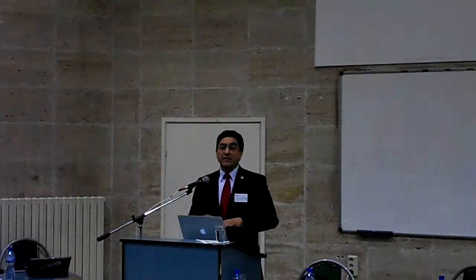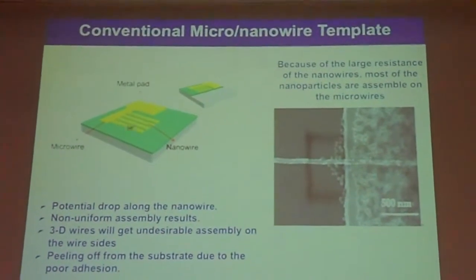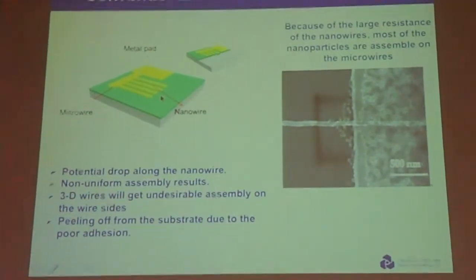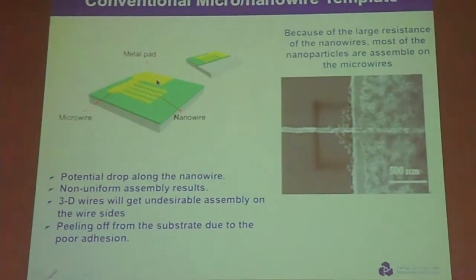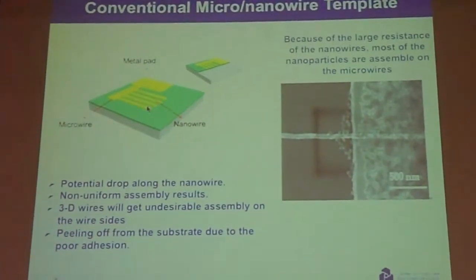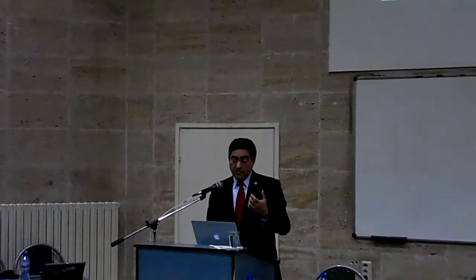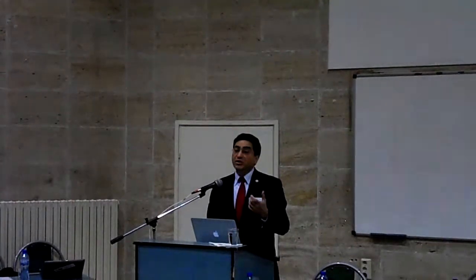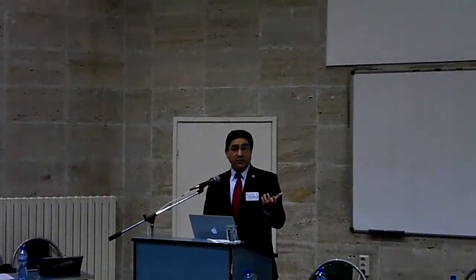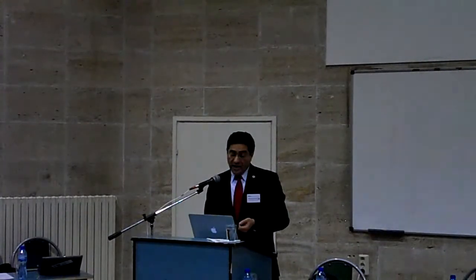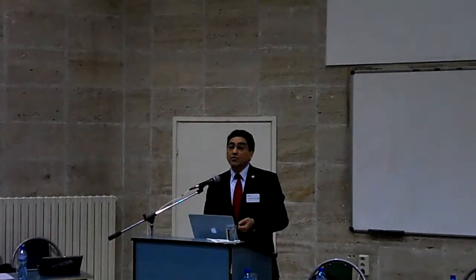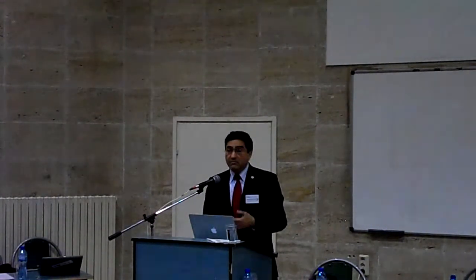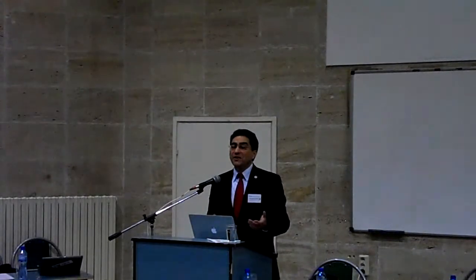So what we did is we had the nanowires, like you see here, on insulator, and we applied voltage, like I told you, 2-3 volts, and it worked for microscale assembly or structure, but it didn't work for small scale. So here, for example, you do the inking and you do the assembly of the particles, for example, on nanotubes. The large structures have the right voltage, but the small structures have such a high resistance that you don't get enough voltage, so you don't attract anything. And you can see here, this wire doesn't have any particles on it. This large structure has lots of wires, lots of particles. So it didn't work. It worked only for micro, but it didn't work for nano.